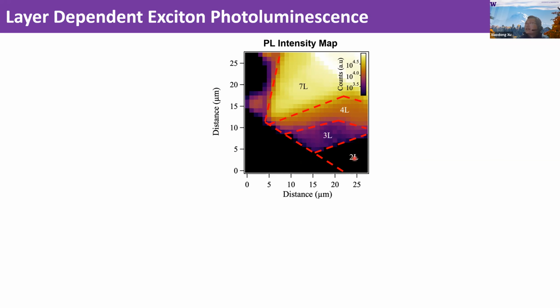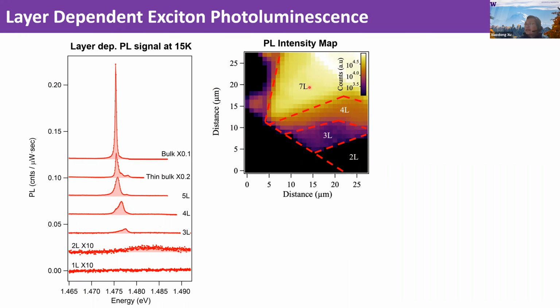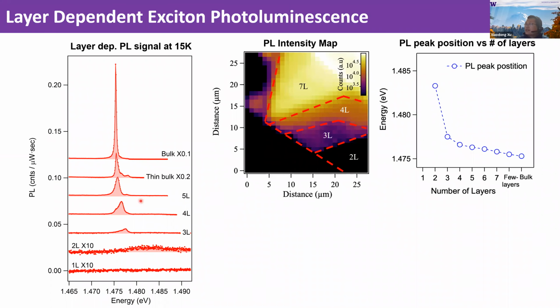So you can extract the spectra as a function of layer thickness and plot it here. From the thin bulk all the way to trilayer, you can see that the PL intensity drops. But what's really dramatic is that from trilayer to bilayer, the PL intensity decreased by an order of magnitude. And from the bilayer to monolayer, we basically don't see anything come out from the samples. So this data indicates there's some kind of electronic structure transition from trilayer to bilayer and then bilayer to monolayer.